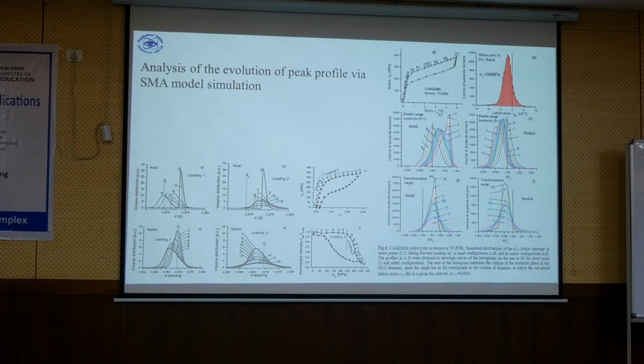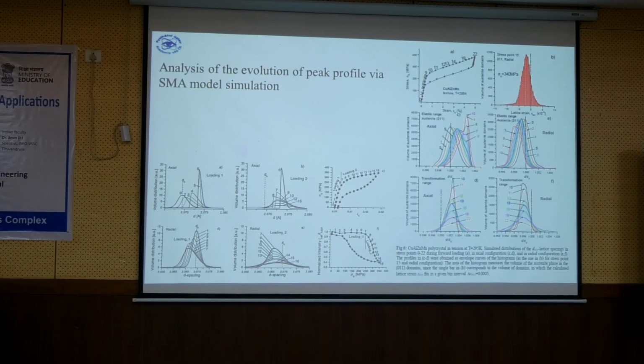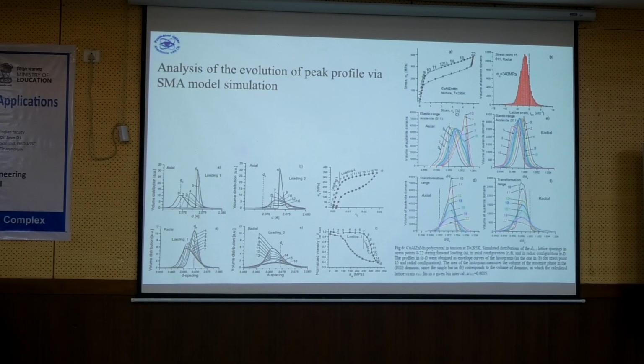Exactly, you see here that in the beginning it was quite broad, and at the end it becomes very narrow. So you may ask why. As I said, you are loading the crystal and you have the break. The peak shifts, and then comes to the break. The break is the phase transformation. Any domain which feels the stress will go down, will disappear from the spectra because it transforms to the martensite. So as it moves, it becomes narrow.